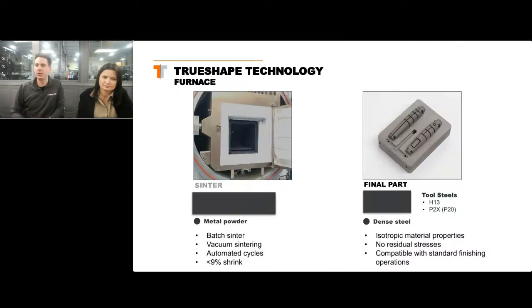After printing is complete, you're going to put your part into a furnace. This is a sintering furnace. If you're familiar with powder metal or metal injection molding, it's going to get just below the melting temperature of the material. The part's going to shrink about 9% here, which is very low, actually, for sinter-based technologies. It is where we're losing our tolerance, which is why that tolerance is plus or minus 1 thou per inch, because shrinking 9% of a 6-inch part is a lot more than shrinking 9% of a 3-inch part.